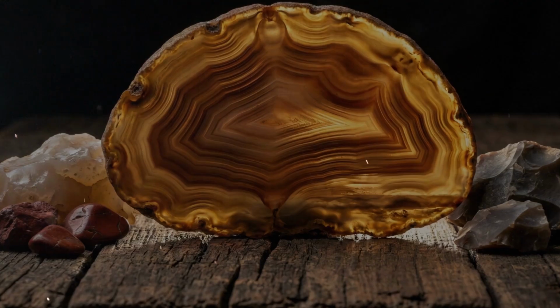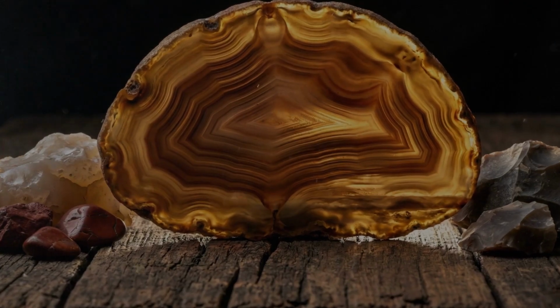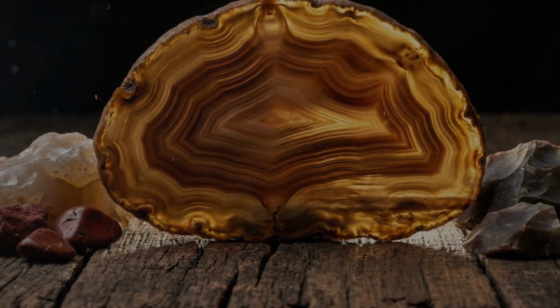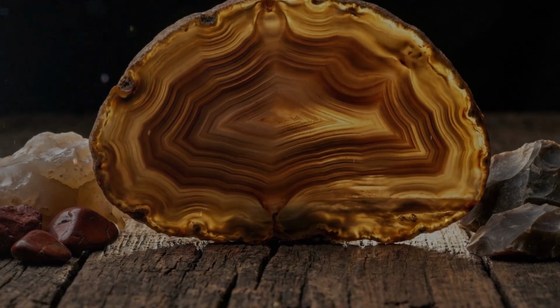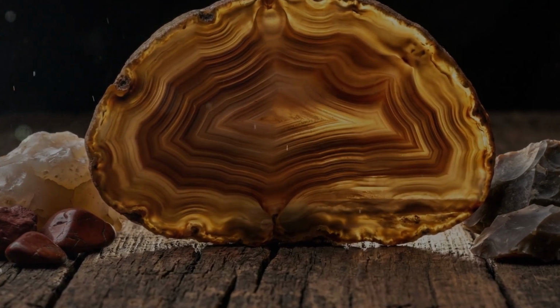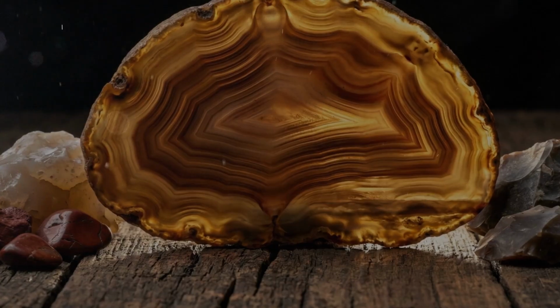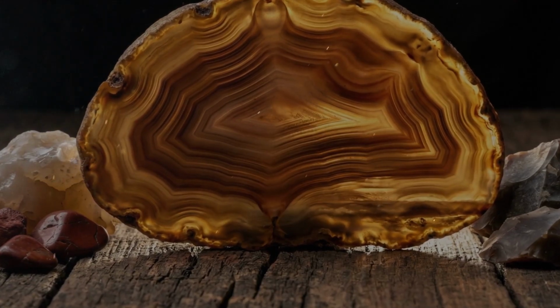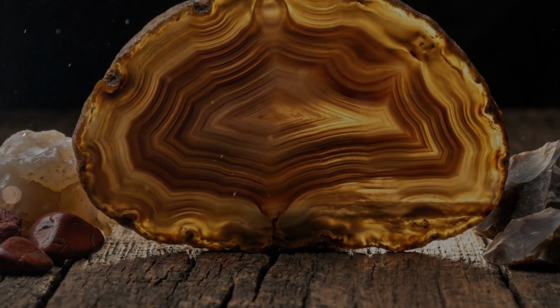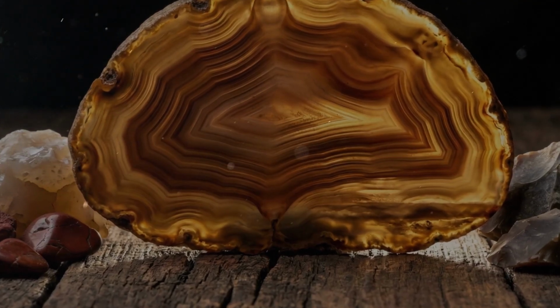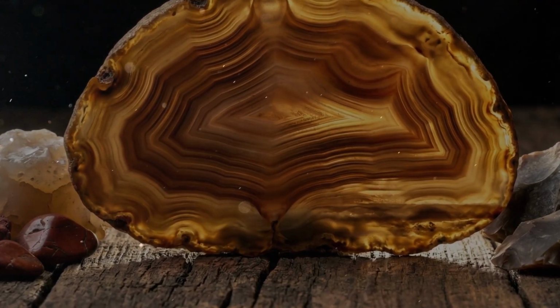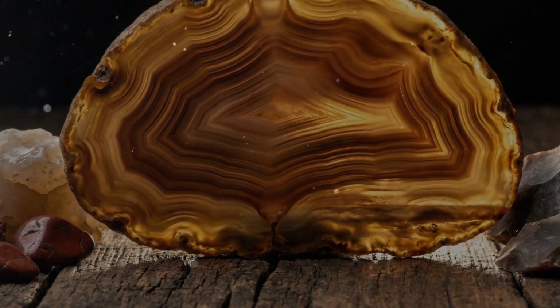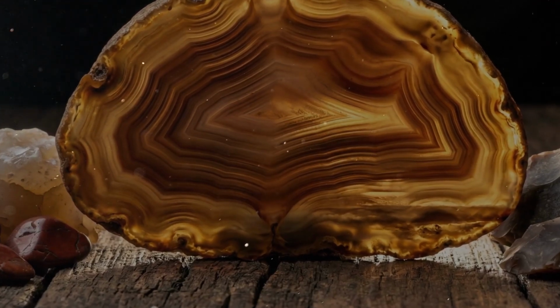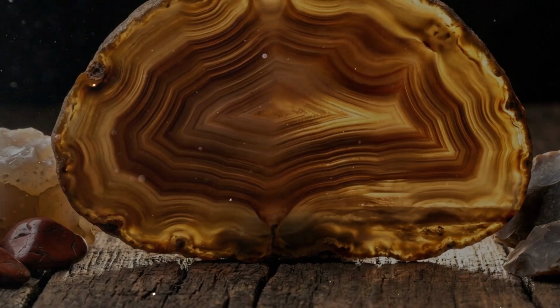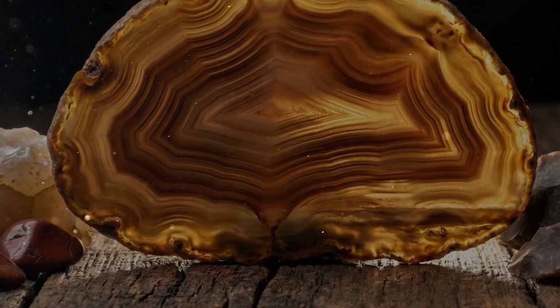They're slightly more porous, making them more susceptible to dye treatments. They have a waxy luster rather than glassy. They tend to be tougher, more resistant to breaking, even though they're the same hardness, because the tiny interlocking crystals resist fracture propagation. This toughness made jasper, agate, and flint ideal for ancient tool use and decorative carving.